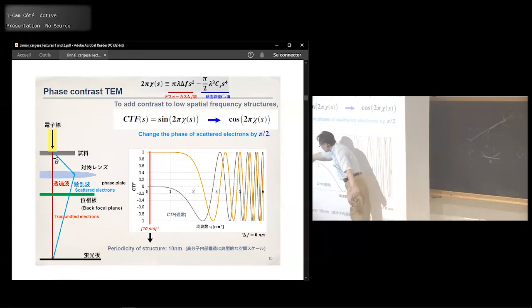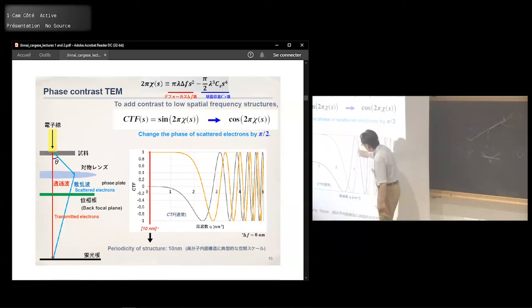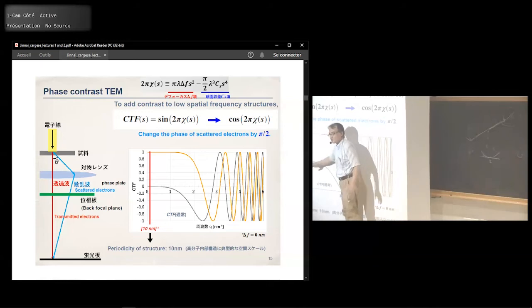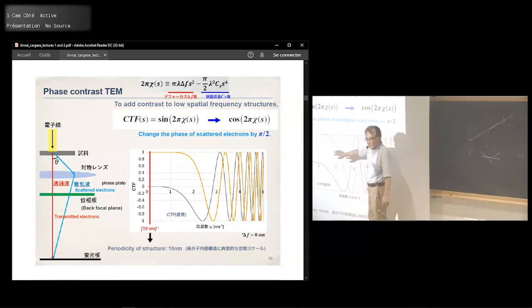So the CTF, this contrast transfer function, is normally these gray lines. At the higher angle, corresponding to small structure, we have an up and down. And this 1 and -1 correspond to either dark or white. Here at 0, there's no contrast. That's what the contrast transfer function means. For the higher angle or smaller structure, there are many bumps. So if we set the optics right, then we can have either 1 or -1, and then we can image with the phase contrast.